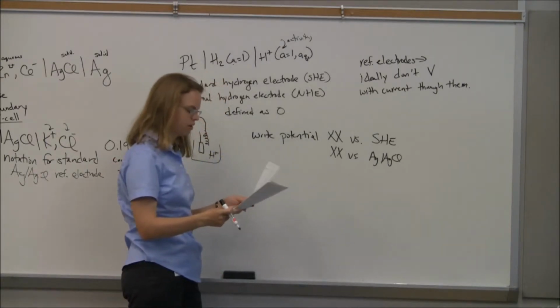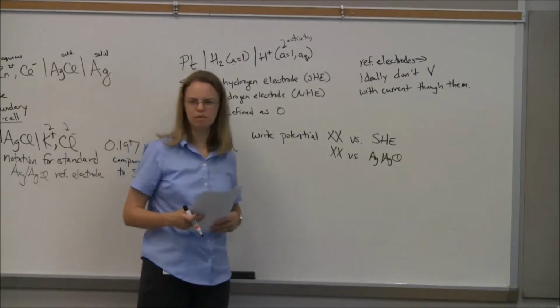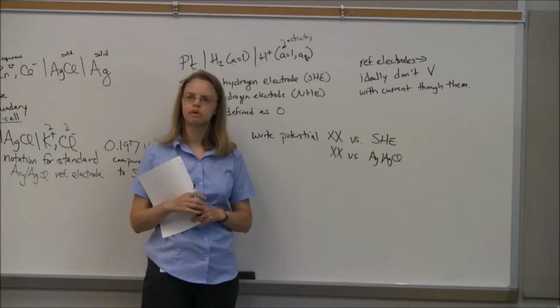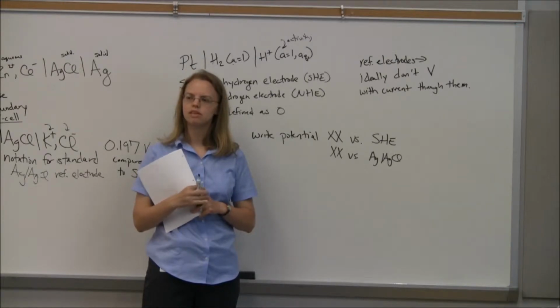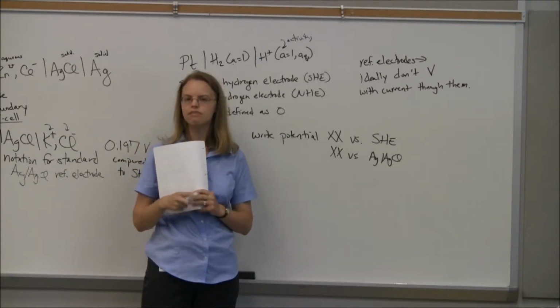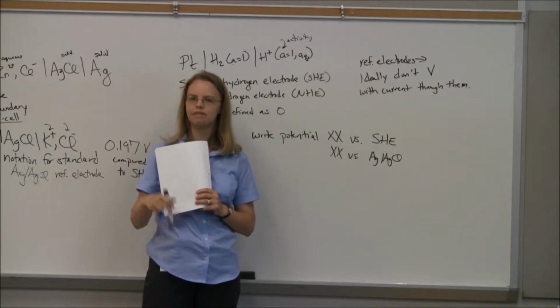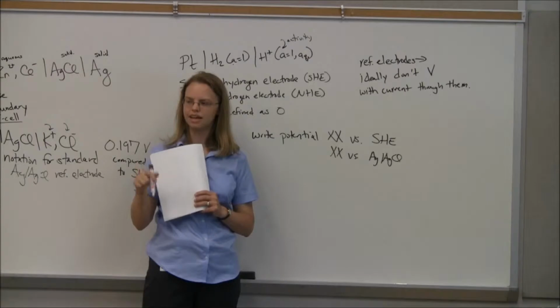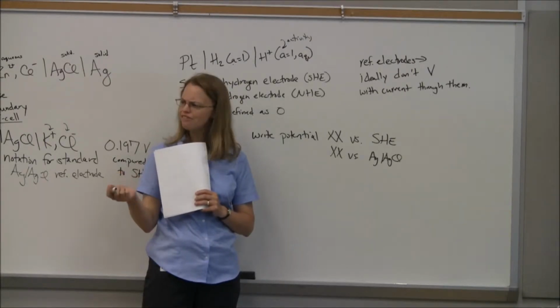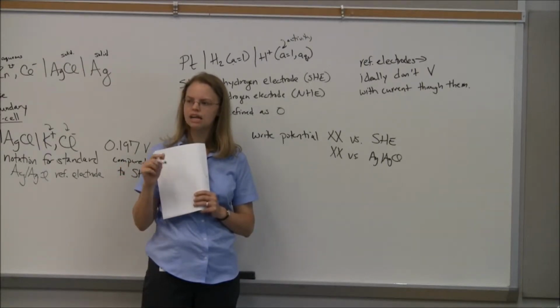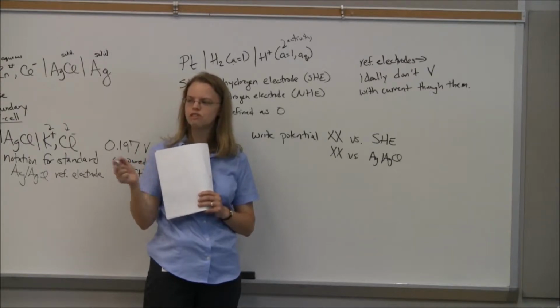Again, we don't typically change the reference, although we tried one time. Megan and I tried a project where we were going to change the reference. It never really went very far. Turns out, this is my hint of the day for in vivo electrochemistry: you can't implant silver chloride into an animal long term and get the same potential out. But Reitman's group just published a paper that if you coat the reference electrode, it's okay. I believe that you get silver oxide, and the potential shifts in a manner.